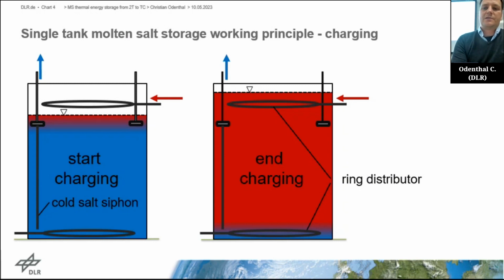Now, what we are looking at DLR is the so-called single tank thermal energy storage concept. And here you store the hot and the cold molten salt together in one single tank. And that is working because hot salt has a lower density than the cold salt. So the difference is quite high. It's about 10% in density difference. Because of that, you can have the cold salt on the bottom and the hot salt on the top. I always compare it with a latte macchiato. So there you also have cold milk and you put hot coffee on top and it remains stratified unless you start stirring it.